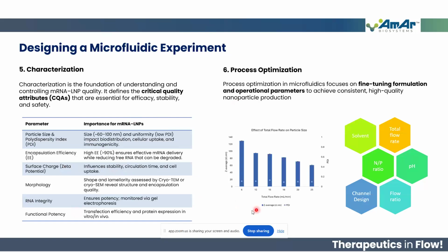And as you can see in the graph, we have used a microfluidic process to optimize the particle sizes. So as we can see, with increasing flow rates, the particle size decreases. And this is only one parameter that we can optimize. In a sense, there are multiple parameters that can actually be influencing your particle size and your encapsulation, such as the microchannel design, the solvent type, the flow ratio, and so on.